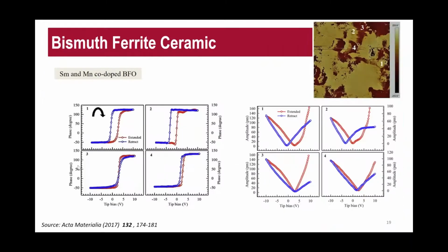And moving from here is another type of bismuth ferrite ceramic. It's an Sm and Mn doped BFO, and we use PFM to study this material, and we are actually able to provide a 2D image, and this is an OOP orientation. What we see is that we are looking into 4 points here: point 1, 2, 3, 4. That means we are doing a localized region, and for each of these individual regions, we obtain the hysteresis curve and also the corresponding amplitude information. There's strain information as well.